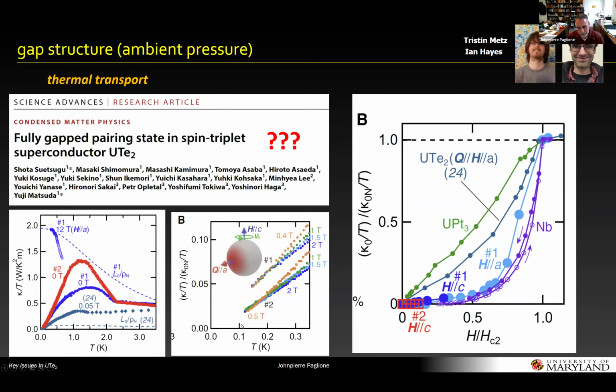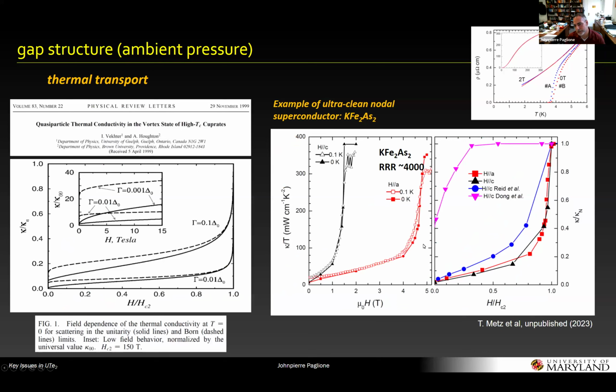So first of all, the conclusion is based mainly on this magnetic field dependence shown in red here of the extrapolated thermal conductivity to zero temperature as a function of magnetic field. So the claim is that if you extrapolate this data, it goes to zero and it rises very slowly with field. In fact, it doesn't rise at all until you get to something like a quarter of HC2. I'll leave it up to you to decide how you would extrapolate this data because there are no extrapolations given in the paper. And I just note that the data doesn't go below about 100 and something millikelvin, so you have to imagine what's happening below that. But luckily we were doing the same experiments, and I'll show you the results of that.